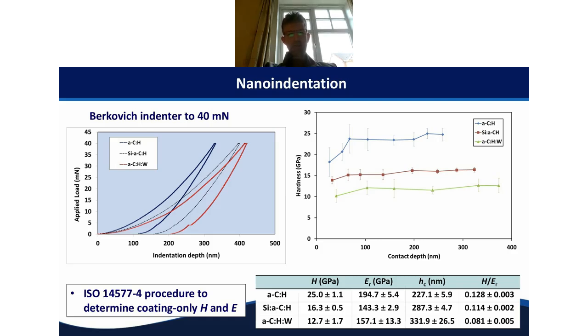If we look at their mechanical properties, we can see on the left that the undoped DLC is more resistant to indentation contact, and when you analyze the curves, it typically has a hardness of about 25 gigapascals, and the softest at the other end is the tungsten doped one, which is about 13 GPa. You can see on the right the mechanical properties as a function of depth, from indentation depths to different load levels, and they're relatively invariant as a function of depth in this range. This is all under 1/10 of the coating thickness. Also you can use ISO type approaches to get accurate elastic modulus measurements, and that was important when we simulated their behavior.